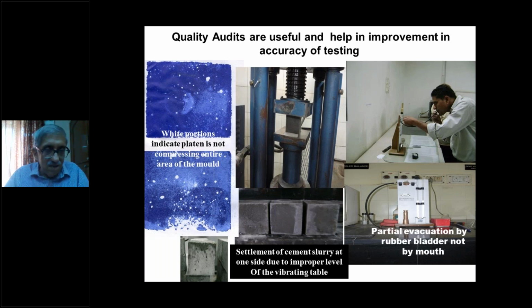And wherever there are white marks, the compression testing machine does not give load on those places. As a result, the area taking the load reduces, and therefore the stress measured is much higher and the cube crushes, but indicates that it is having low strength. Really, it is not, because if the machine platens were tested the way I showed you, it would be a different story. You'll get the correct reading.